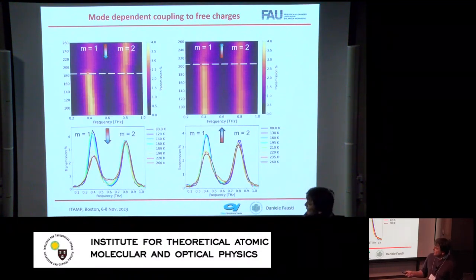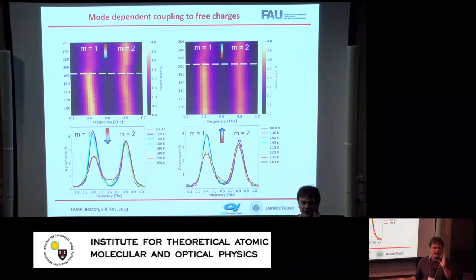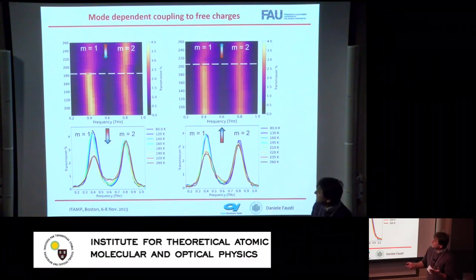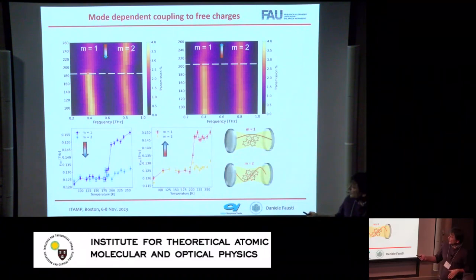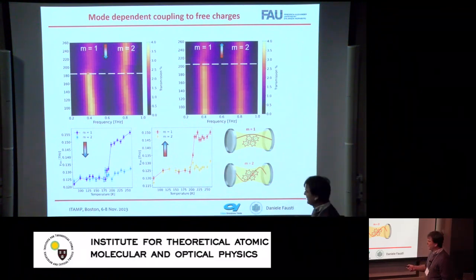But what's most interesting is if I try to go in a situation where I see both the fundamental mode of the cavity and the second mode of the cavity, I realized that the fundamental mode of the cavity is very sensitive to the presence of the metallic or insulating state, while the second mode of the cavity essentially ignores the fact that the layer I have in the middle is metallic or insulated. And how do I understand this? I understand this because the second mode of the cavity has a node in the middle, so essentially it ignores if the object in the middle is a metal or an insulator because it has a node anyway. So that proves in some sense that I'm sensitive to the mode structure.